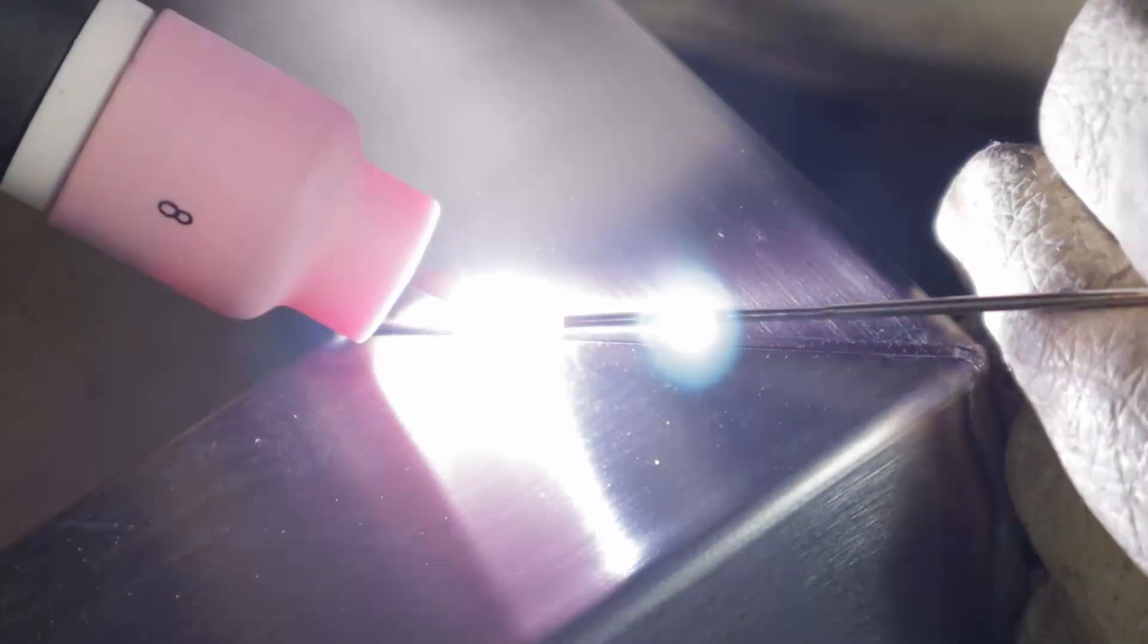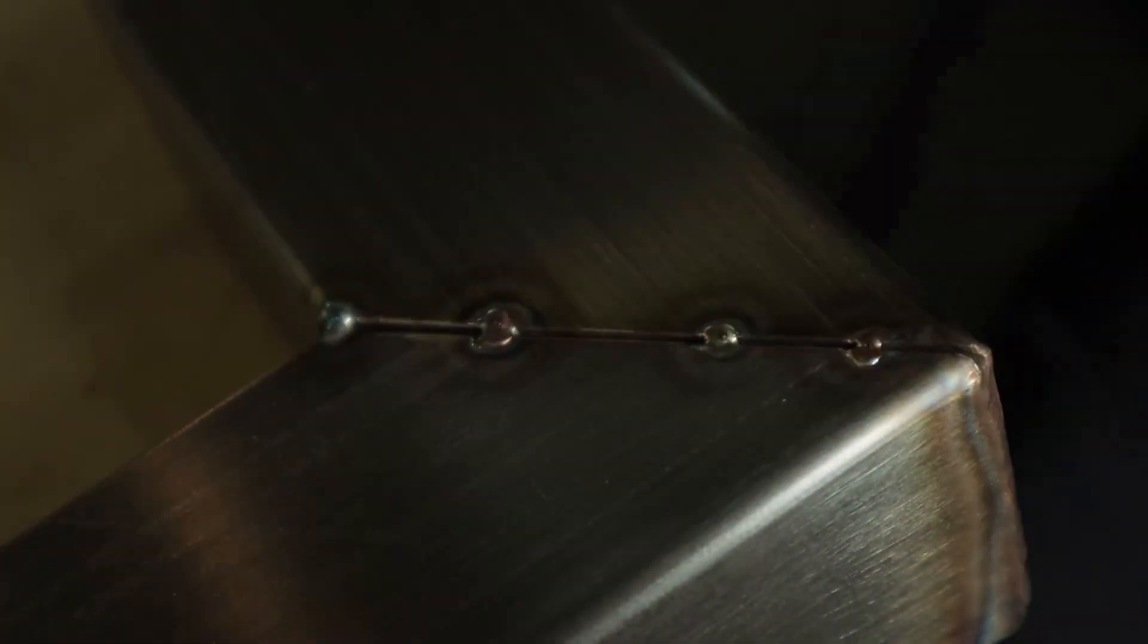I've changed position for this joint to make it easier. Next to close the gap up. Before welding clean the tacks with a wire brush to remove any dark grey colouring and this will help getting the puddle established quicker. This will create more distortion though.